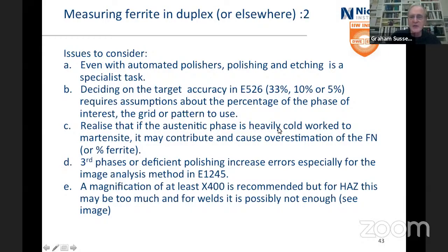And you should realize that if the austenite phase is very heavily cold worked, then that may have generated martensite, which might overestimate the ferrite. If there are third phases or poor polishing, then your errors get worse.